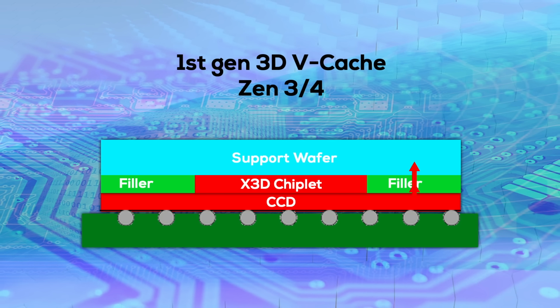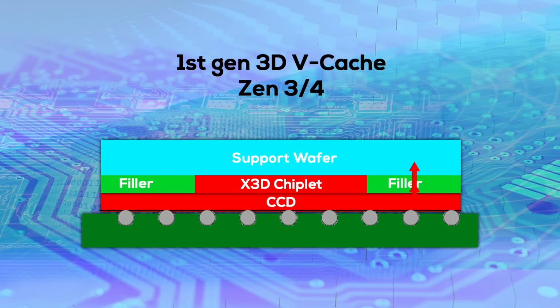Silicon on its own already isn't that great of a thermal conductor, but it's not horrible either. But these oxide layers are real thermal barriers that block the heat from moving upwards. The cache isn't a problem. The silicon isn't either. The bonding layers are.